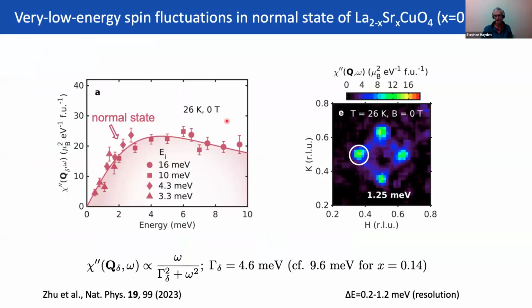So if we just home in on one of these peaks, this peak here, and plot the data as a function of energy, this is the spectrum we get, and you can see there's a lot of spectral weight, and the characteristic energy scale that we could read off this is about 4 or 5 milli-electron-volts. So we can fit it. Actually, it fits very nicely to an overdamped harmonic oscillator, a very overdamped harmonic oscillator, that is a Lorentzian function, and we find the energy scale is less than 5 milli-electron-volts, so much less than, a factor of 2 less than, the underdoped side of the phase diagram.